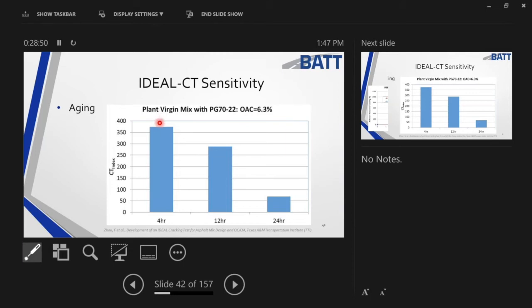Here's the aging component. So 4 hour may be my standard aging, but what happens, and notice here, we did change to a 70-22 with an optimum asphalt content here of 6.3. Notice what happens when I go 12 hour aging and 24. Why in the world would I ever want to do that? Well, let's walk before we run and get the 4 hour stuff down first. But is there a point where I ever want to design maybe with 12 hour aging or 18 or 20 hour aging, even 24? Absolutely, because that's going to pick up on some of the effects of the REOB or other recycled products that may break down over time that we need to look at. Again, let's walk before we run on this. Okay.